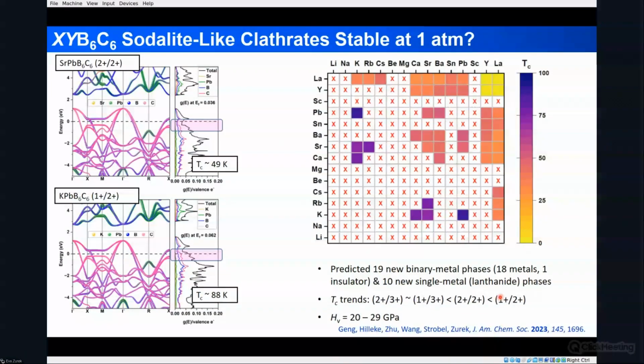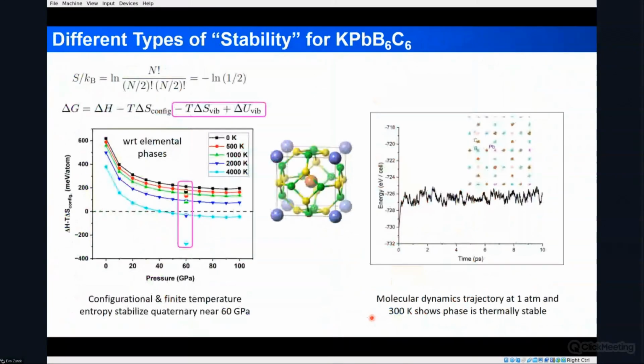Okay, so these are some of the trends that we've noticed, and we've also taken a look at the Vickers hardnesses. And as I noted before, it's important to think about different ways that stability is defined. Though this potassium lead compound is dynamically stable at 1 atmosphere and also stable according to the molecular dynamics simulation, if you take a look at just the enthalpy of formation, it doesn't suggest that it's going to be stable.